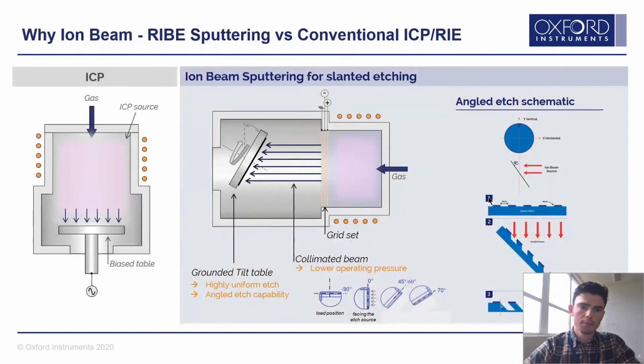So why ion beam? Why use this reactive ion beam sputtering versus a conventional ICP? Well, on the left, we can see the conventional ICP system, and everything's in one chamber. We generate our gas, draw the plasma down towards the table using a bias voltage, and this is going to be orthogonal to the surface. We're going to have a perpendicular etch direction. So if we wiggle the table around, tilt it, move it around, we're just going to get that perpendicular etch no matter what we do.